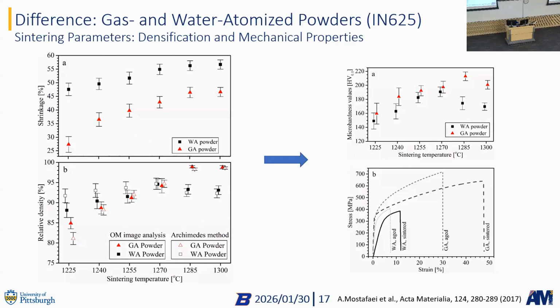And what we also saw is, even though we might not be fully dense, we can still, after sintering, age our material to change the properties of these metals, right? We can make them a little bit harder, increase UTS, which would result in less ductility. But still, we can modify through aging after sintering as well.